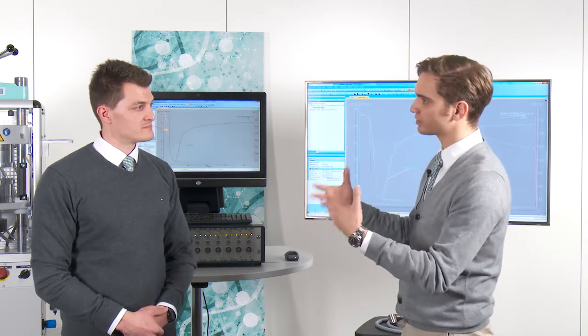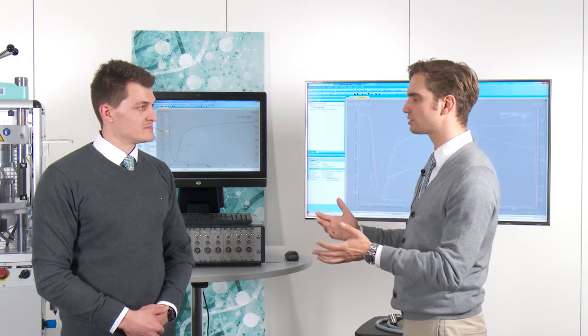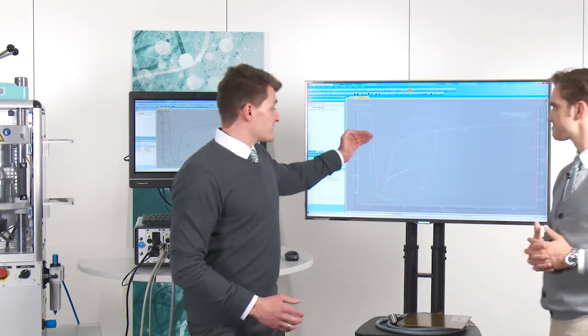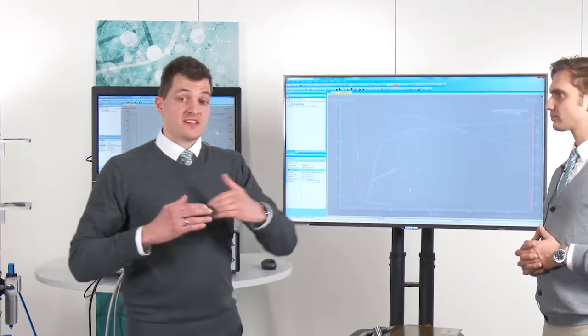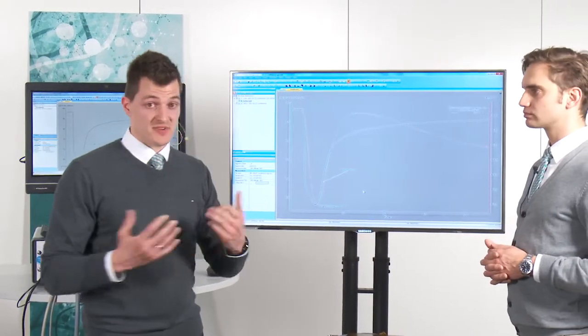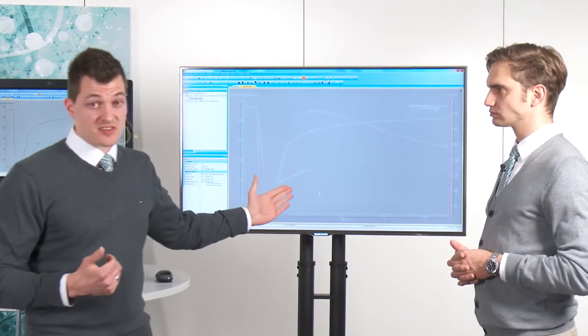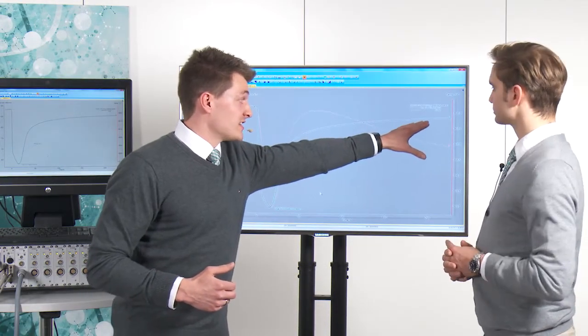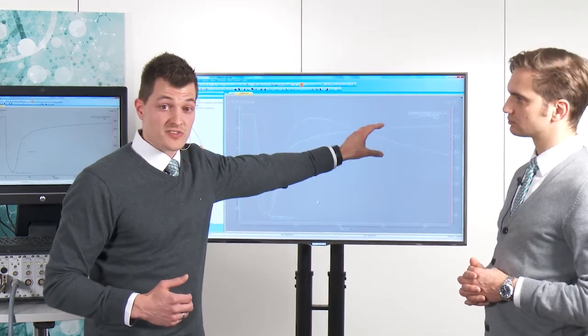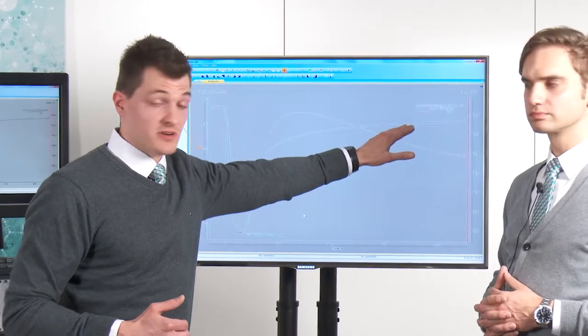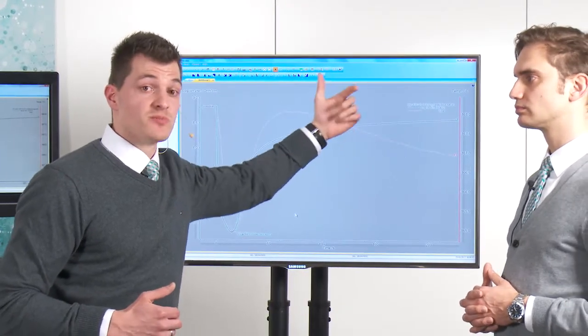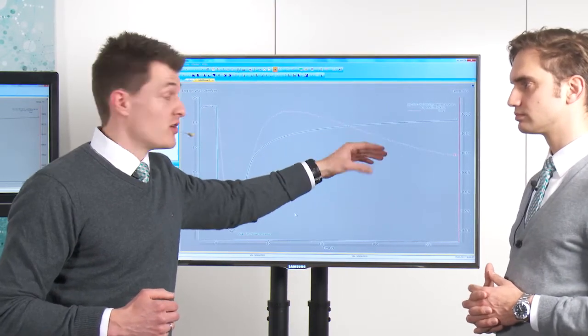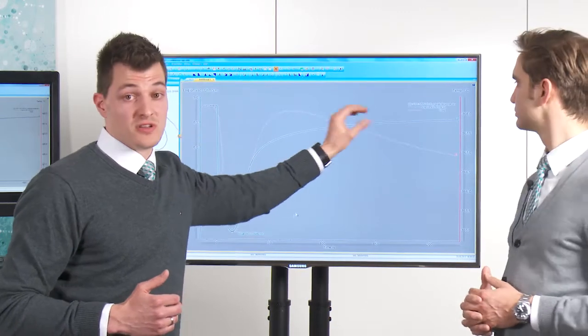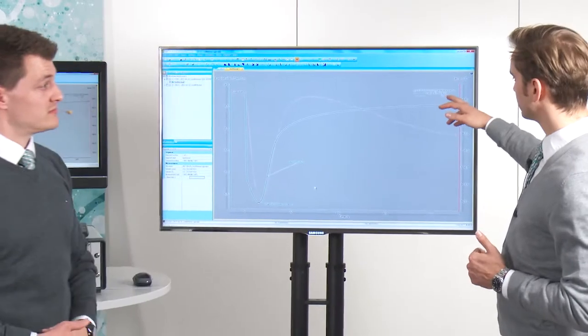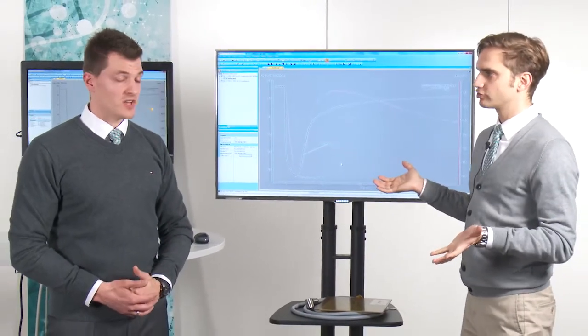Secondly, concerning the frequency, you selected one frequency, but generally dielectric measurements are multi-frequency measurements. How can I know about the frequency? Yeah, the frequency response is such that the higher the frequency, the lower is the response we get from the sample. So, for example, here we can see a very good dielectric signal of the sample. But if we reach a horizontal line here at the end of the cure for this 10 kilohertz curve we used now, then we cannot follow the curing process anymore with this frequency. So then we can switch to smaller frequencies, for example, 100 hertz, 1 hertz, or 100 millihertz, and then we can follow the post-curing process of this material. Okay, well, this was an epoxy, 10 kilohertz is an appropriate frequency, you would say.